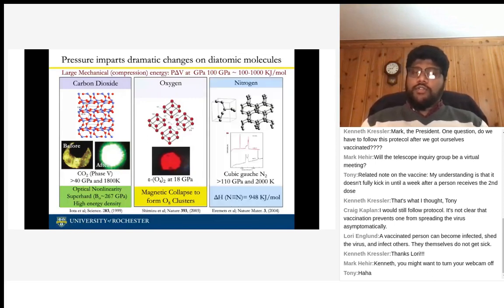And then if you take a simple material like nitrogen gas, nitrogen has the strongest triple bond. But if you subject it to really high pressures, you break this triple bond and it becomes single bonded nitrogen, then all of a sudden you are in a different chemical world. There's an enormous amount of energy stored in these materials, and when you release it, you can get this energy back. It's a highly packed, high energy density material.